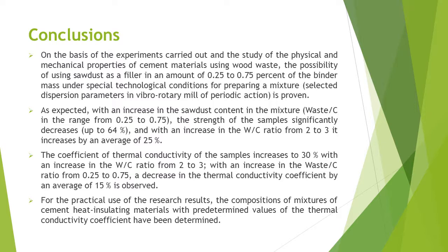The coefficient of thermal conductivity of the samples increases to 30% with an increase in the water-cement ratio from 2 to 3. With an increase in the waste-cement ratio from 0.25 to 0.75, a decrease in the thermal conductivity coefficient by an average of 15% is observed.